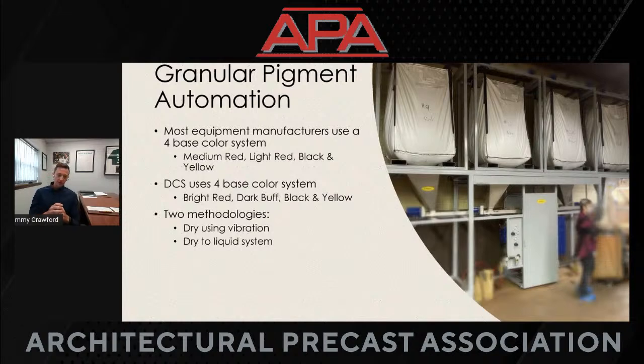Again, there are 2 methodologies here, one using vibration and one using a dry to liquid system. Basically, with vibration, you vibrate the trays that the granules sit in and drop them down into a weigh hopper. Liquid is a similar idea. You weigh the material, then you liquefy it and pump that liquid up to the mixer.